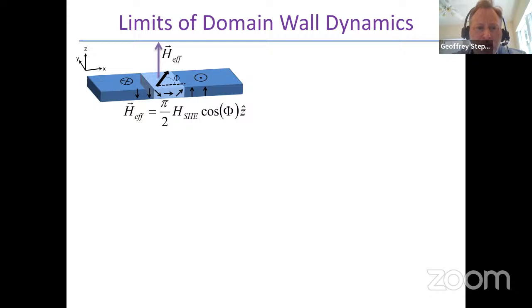So in conventional domain wall dynamics, I mentioned early in this talk this idea of domain wall stiffness. When you drive a domain wall, if you start with a domain wall that is Néel, then in the schematic that I've shown here, the moment of that domain wall would be pointing from left to right. So we've got a down domain, an up domain, and as you walk across the domain wall, at the center of the wall, the magnetic moments would be pointing right.